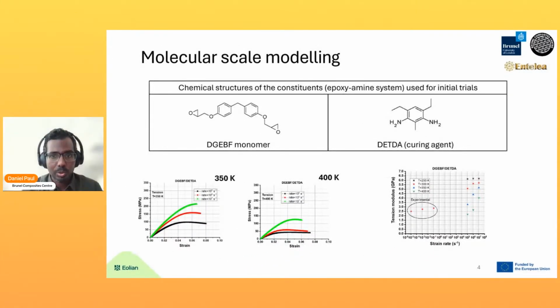But as you can see, these results are obtained at very high strain rates. They are around 10 power 6, 7, even 10 power 10. We cannot perform the molecular scale simulations at the experimental strain rates, which are more like 10 power minus 2 to 10 power 2 or 10 power 4 at the maximum. So there is a discrepancy between what results we get from the atomistic scale and the properties that we need to perform FE analysis or to compare with experiments.